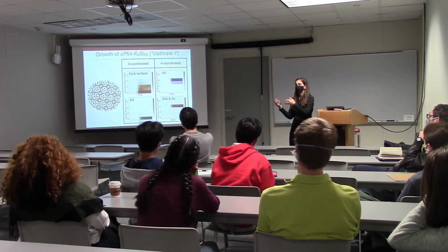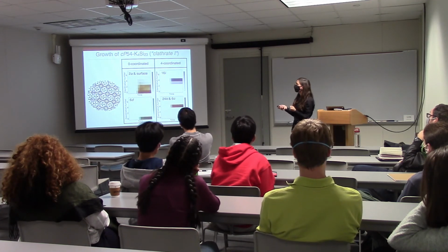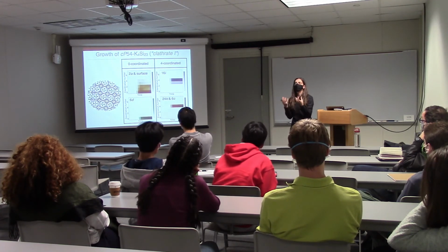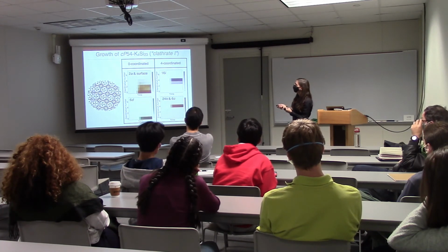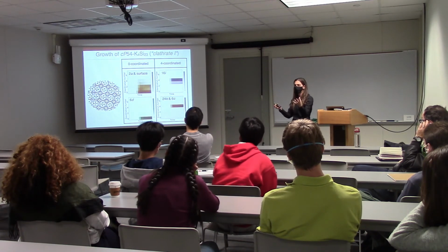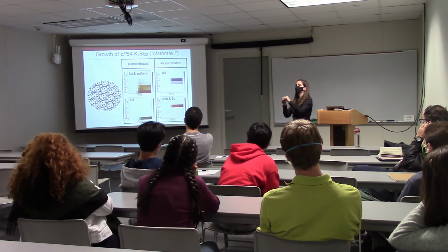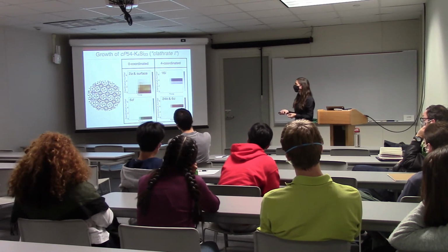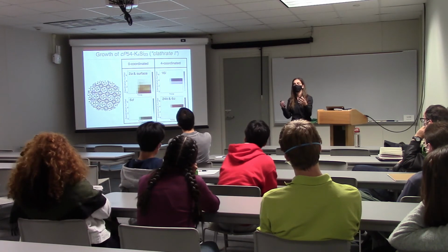What we can do with this now is say, okay, do they behave differently from one another? Because we have particles that are in slightly different symmetrical positions that are effectively equivalent, but some of those particles are zero coordinated, so they have their first neighbor shells empty and they sit in these huge cages in the clathrate. And the other particles are four coordinated, they form the framework that makes up the clathrate. And they really differ in how they behave once they're part of the crystal.